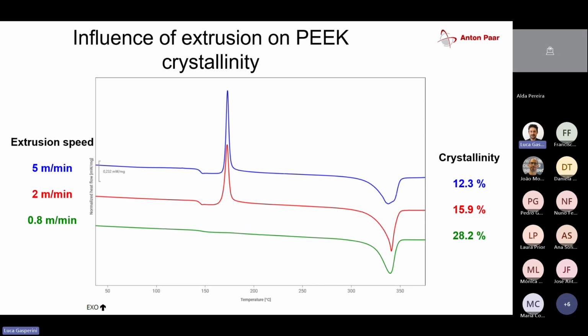And then the final product was measured using the DSC again. And we see on the first 2 curves, the blue and red one, 3 effects. First one is the glass transition, quite nice. And then the second, at temperatures above 150 degrees, we see an exothermic peak of the cold crystallization.